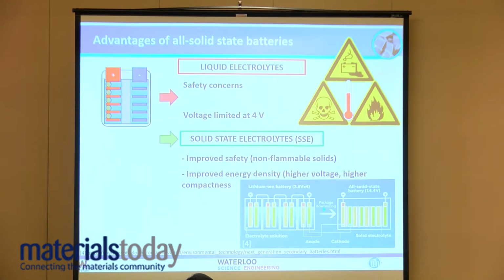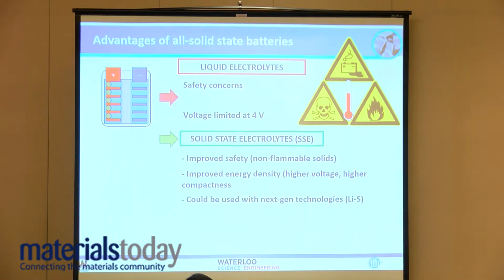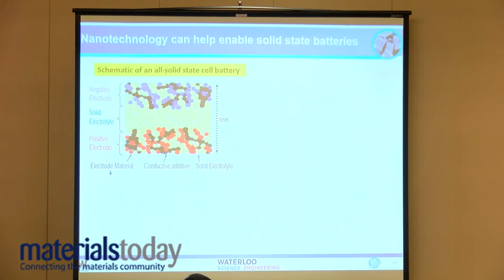So you can go from a situation in which you have a typical stack of cells for a lithium-ion cell, and now these are simply stacked in planar arrays. And just that design feature itself really improves the volumetric energy density. And they are quite compatible with next-generation technologies such as lithium-sulfur. And what might surprise you is that they have better low-temperature performance, as Toyota has shown, simply because the ions are moving through a solid and they're not limited by the viscosity of liquids at low temperatures.